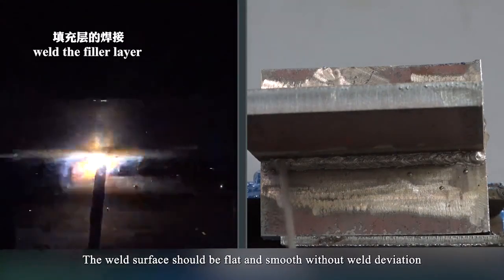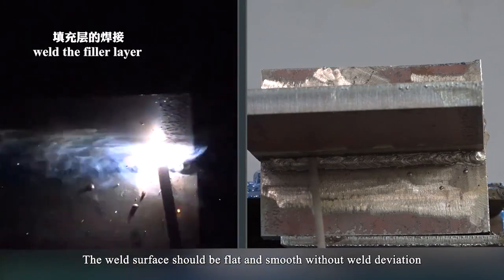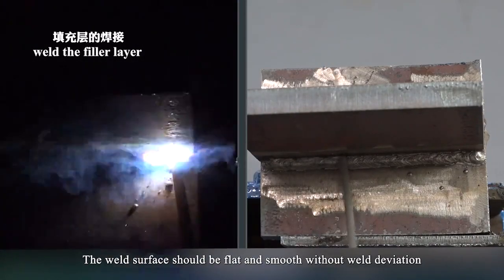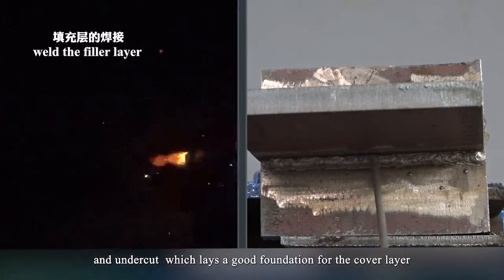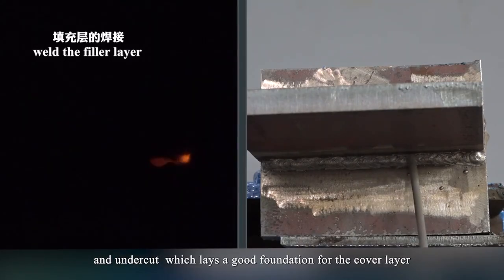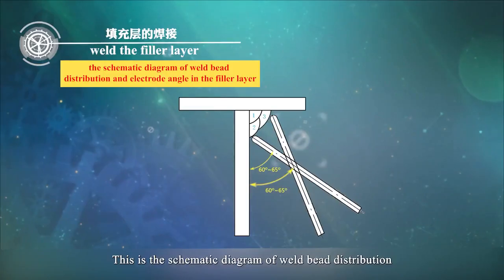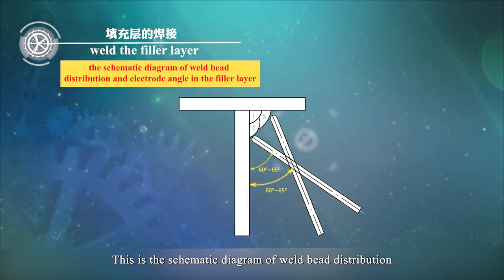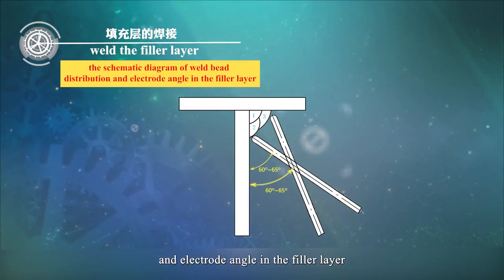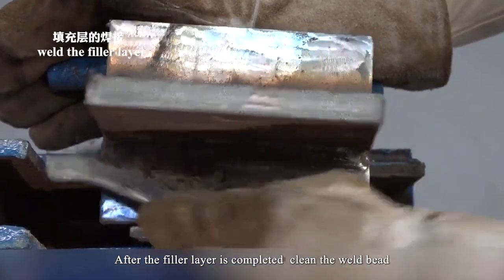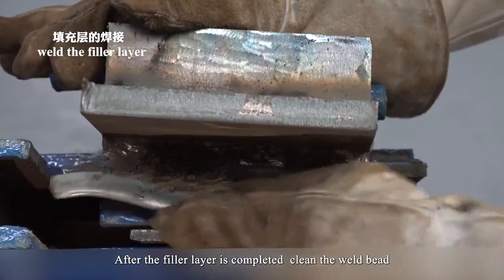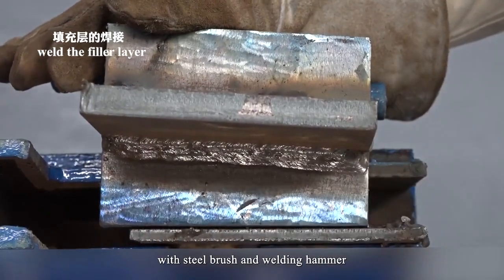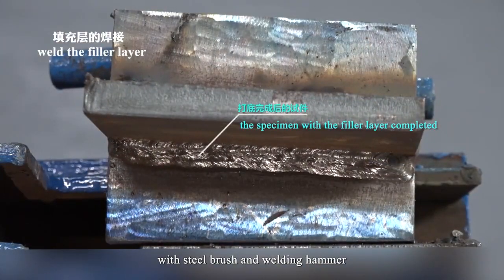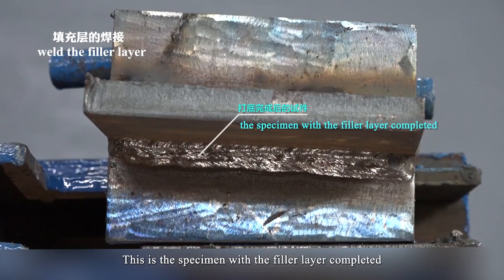The weld surface should be flat and smooth without weld deviation and undercut, which lays a good foundation for the cover layer. This is schematic diagram of weld bead distribution and electrode angle in the filler layer. After the filler layer is completed, clean the weld bead with steel brush and welding hammer. This is the specimen with the filler layer completed.